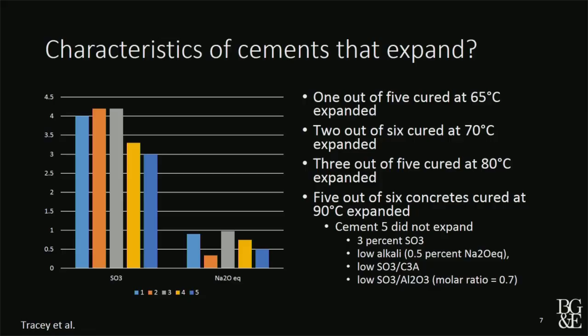So this was one set of tests that was conducted at the company that I left. I set up the program, then left the company. But it's some tests finished by Sharon Tracy and some of her colleagues, where they took 6 different cements with 6 different characteristics and cured them at different temperatures, ranging up to 65, 70, 80 and 90 degrees. And what they found is even at 90 degrees, one of those cements didn't show expansion. Now this correlates with the information we just heard that concretes with low alkalis and low sulfate contents may be less susceptible to delayed etronite formation than those that have high etronite contents.